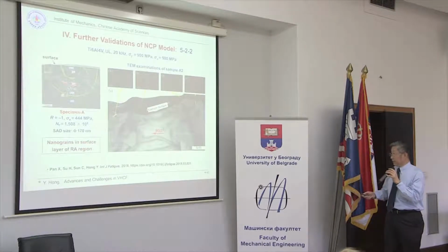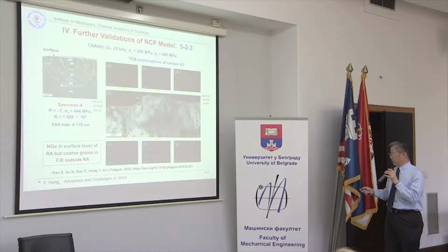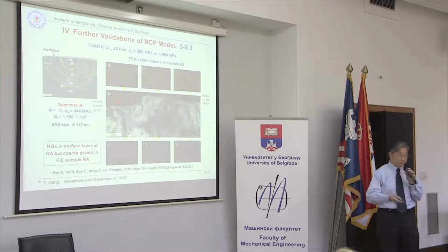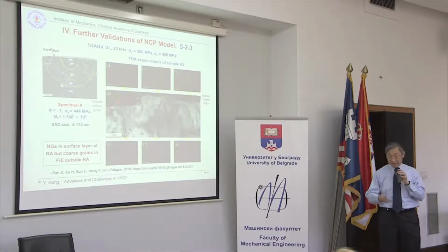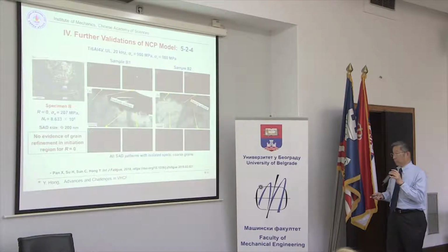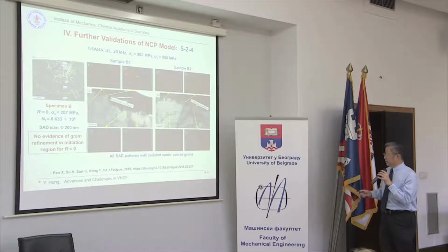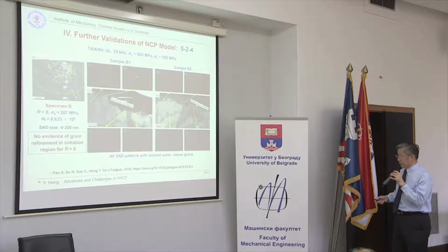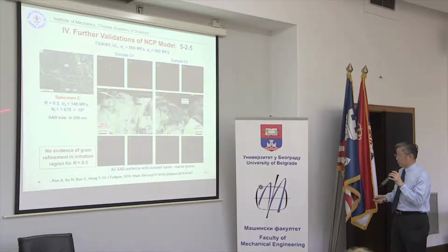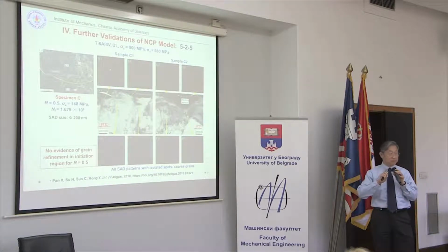And for A2 and also A3 specimens, we may observe microstructural refinement in the layer underneath the fracture surface. And also for positive stress ratios, this is the 0 stress ratio, and especially for 0.1 stress ratio, there is no evidence of microstructural refinement for titanium alloys.